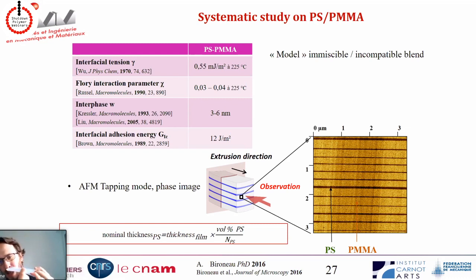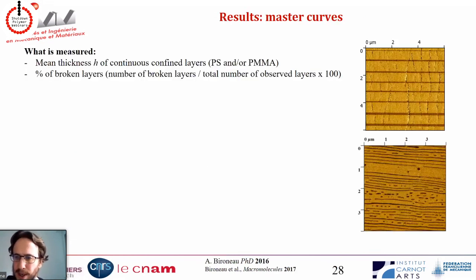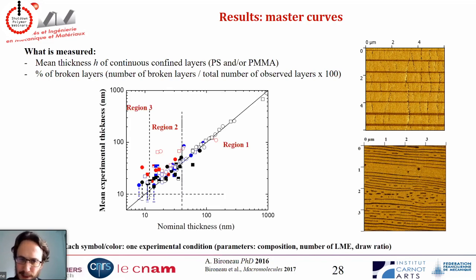So again, AFM observation in the thickness direction. What you can see is that for thick layers, you have a continuous system, and you can measure the thickness of each layer. And you can get some statistical information if you measure a number of layers that is large enough. Now, if you try to tune down the thickness, you will start to see some layer breakups, and you can also measure the thickness of the layers that are not broken, and you can measure the number of layers that are broken. And if you plot that for every parameter condition, you get some kind of master plot. Here in this master plot, we plot the mean experimental thickness, so the thickness we measure via AFM, as a function of the nominal thickness, which is the thickness we wanted to make that can be, in theory, controlled when you control all the processing parameters.